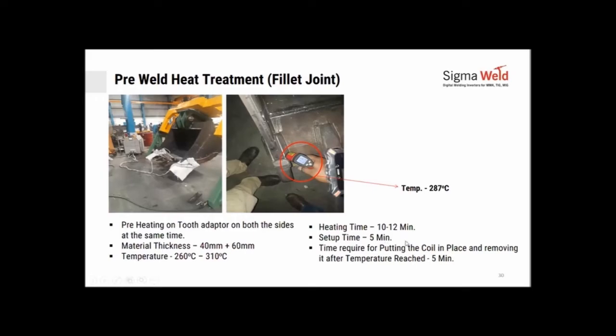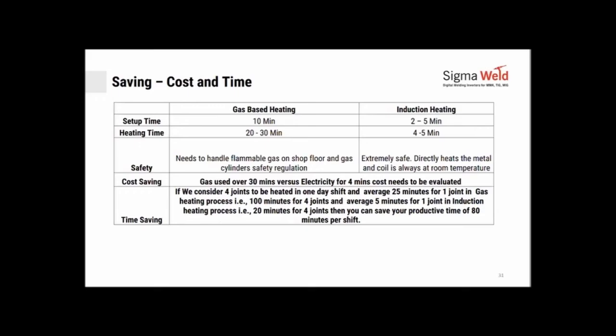Time taken to put the coil in place, to remove and start welding, under 5 minutes. You see, if you were to do gas-based heating, 10 minutes would be setup time. In induction, 2 to 5 minutes setup time. Heating time, 20 to 30 minutes in a gas-based system, whereas 4 to 5 minutes on the induction heater. Safety, the gas flame is always on, so somebody there has to be careful. The surrounding area is getting hot. Here, no flammable gases to be handled on the shop floor, extremely safe as we shared earlier.